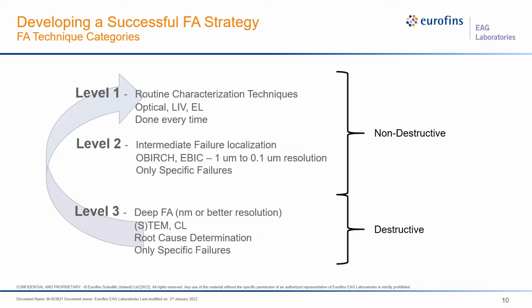And then from there, there'll be another subset of samples that need further understanding. And so we call this level 3 or deep FA. This is where we head into destructive analysis. So we're going to use focused ion beam, dual beam, to cut into the sample and image with SEM to try to understand how the defect is propagating through the epitaxy, et cetera. And then we're going to use scanning transmission electron microscopy, in some cases maybe cathodoluminescence or CL, to really try to get at root cause determination for these specific failures.